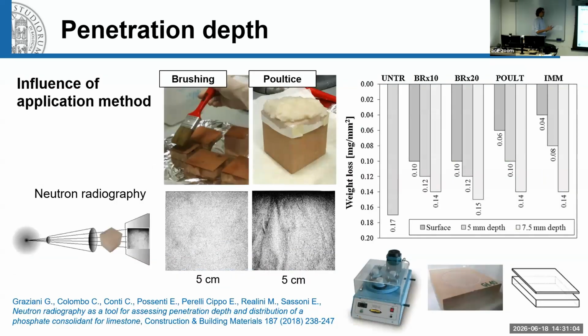So going quickly through these results. Penetration depth. Again, I remind you, the idea is applying a liquid solution that penetrates in depth. Some years ago, we performed a comparative study where we compared the different application methods like brushing or a poultice applied onto the material. And then in this case, by neutron radiography, we were able to see the penetration of the consolidant in depth in the limestone in this case. So the black part indicates the presence of the hydroxyapatite. So the deeper the penetration, the better.